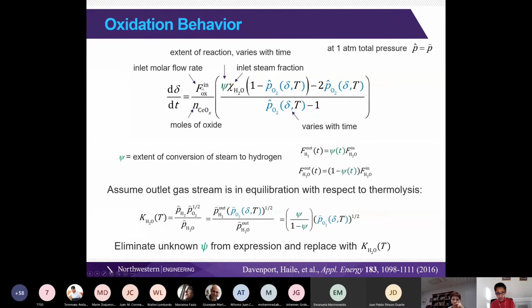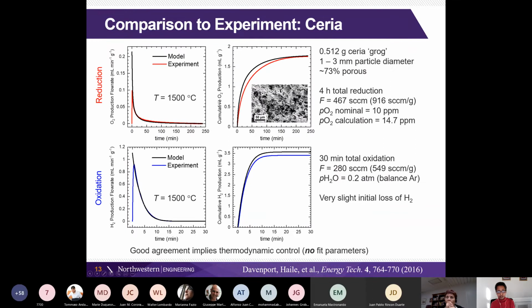Key thing is that the flow rates and the moles of oxygen or oxide that we put into our reactor really matter in terms of the rate of hydrogen production or rate of oxygen release. So here are some comparisons to the experiment. You can see that we do predict our experimental results quite well. So this is the model and this is the experiment.